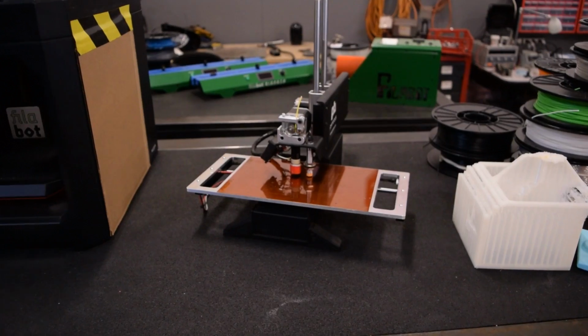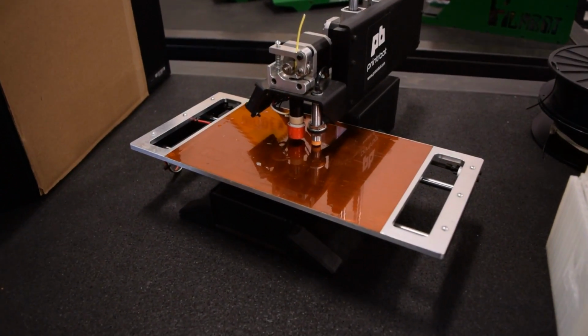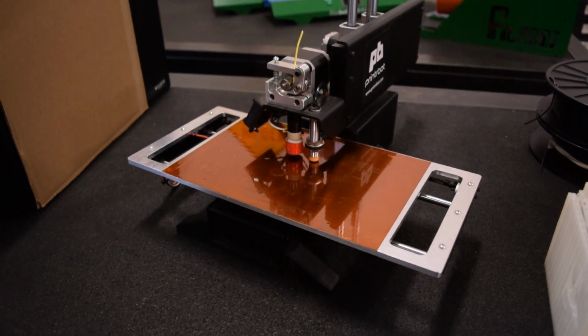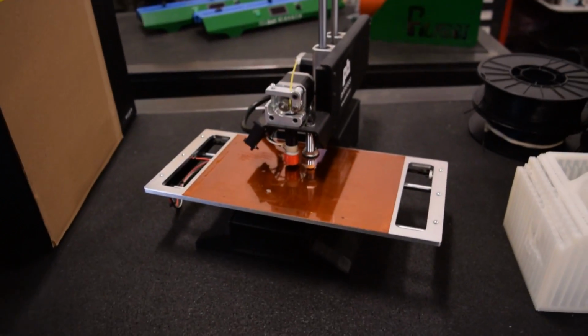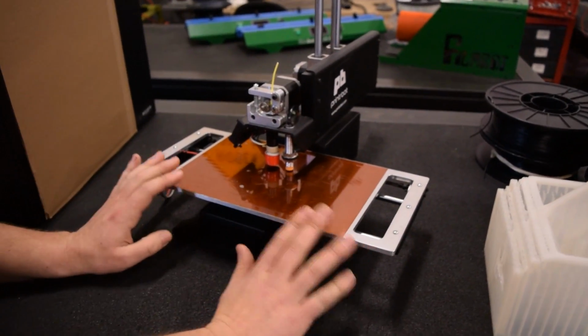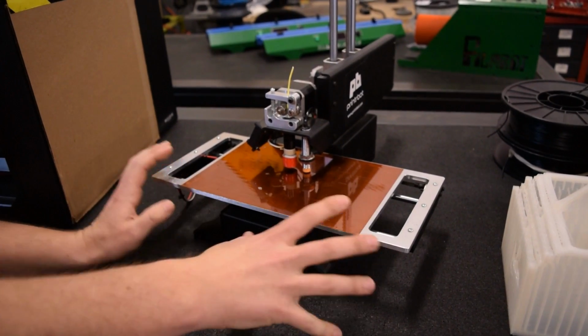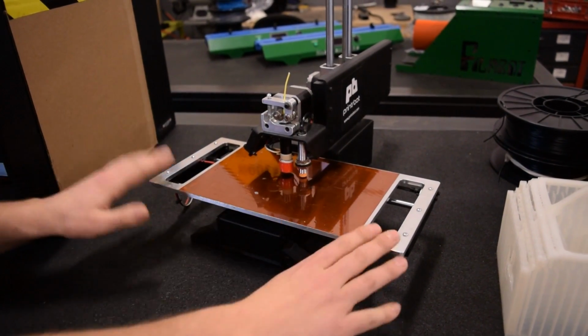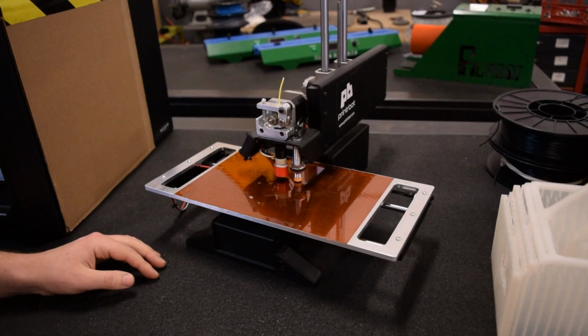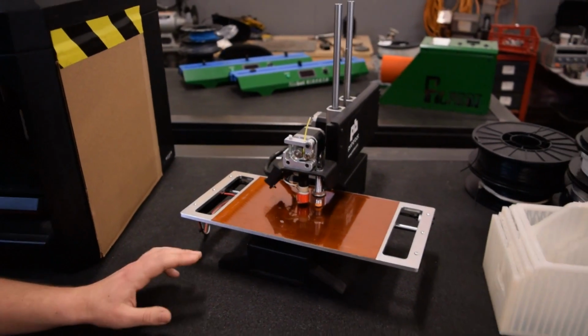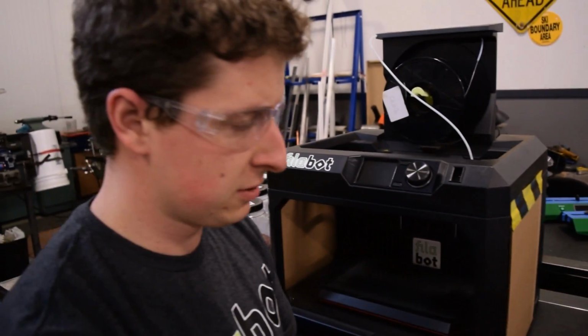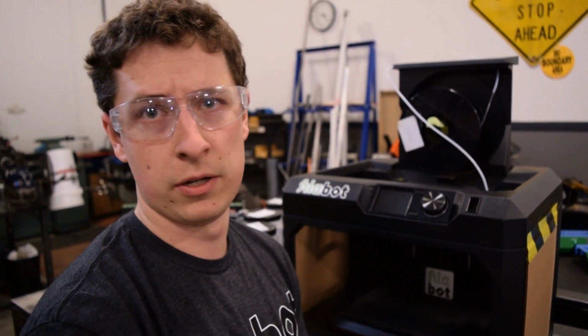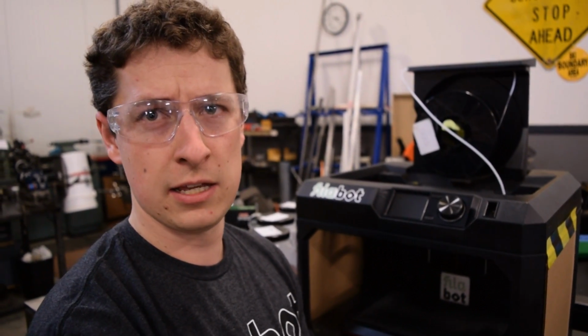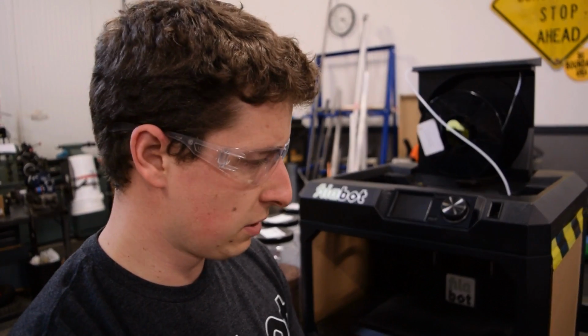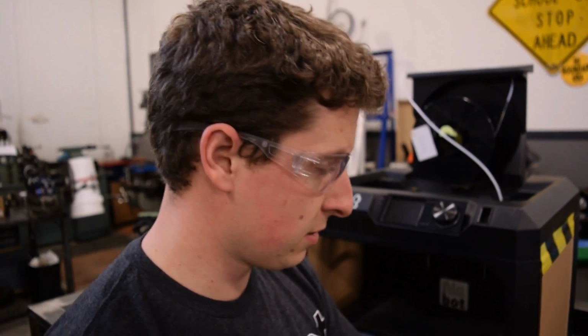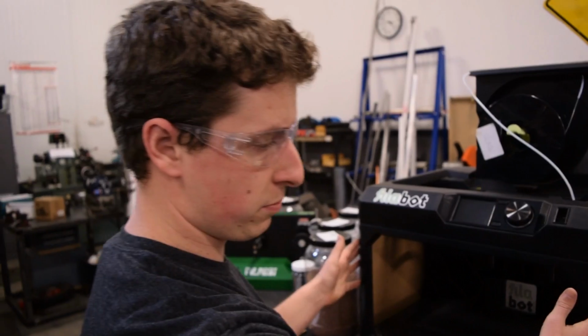Right. But if your printer has a heated bed, that can help keep the environment and the first layer, which is the most important for adhesion, warm. A heated bed actually gets hot. You can program this in the slicing program to bring it to an elevated temperature. What do we print? PLA, we don't really use it. ABS and the more interesting grades of polymers will bring that temperature up. I think 110C is our upper limit that we use. But yeah, that's the heated bed part, and then an enclosure part.